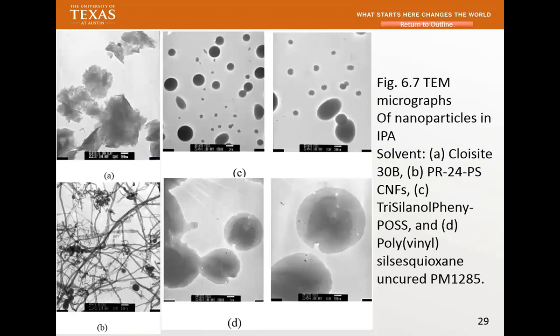All these are different types of nanomaterials we use in my research. Carbon nanofibers, and for the polymer, when you buy them, all these fibers are entangled. You need to break them out a little bit and disperse them. But you don't want to totally break them down. If you totally break them down, you lose this length. So you need to see how well you can disperse. If you have this kind of tangle, you could never disperse it. But you need to break it down small enough, but not make the fibers so short, otherwise you actually have a smaller L/D. So this is something that we use.